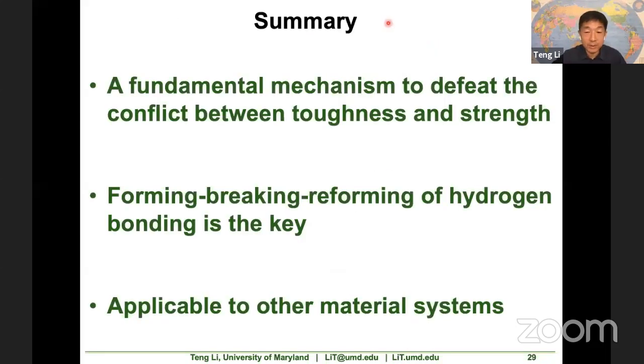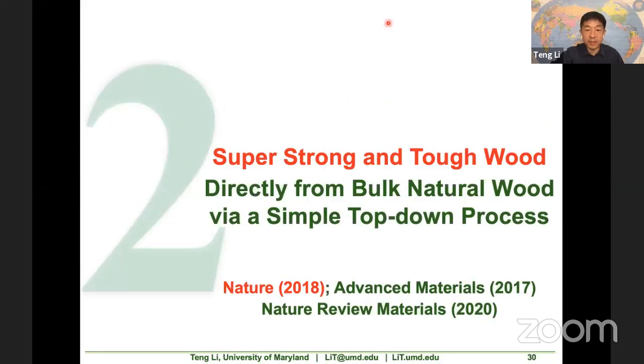So I hope with this I demonstrate a fundamental mechanism to defeat the conflict between toughness and strength. The key here is to allow the hydrogen bond, although it's not the strongest bond, to form, to break, and to reform. And this fundamental mechanism is actually applicable to other material systems. And indeed, there are many, many ways you can functionalize the surface of the building blocks to allow this deformation mechanism to occur. Let me move to the second part.